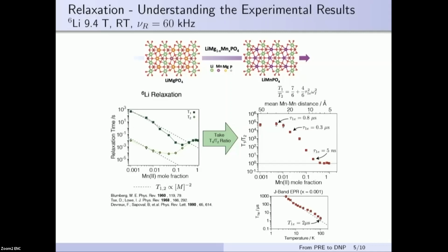So we wanted to know if these estimations are more or less correct. What we did is we were able to do some EPR relaxation measurements at high fields for the lowest concentrated sample for temperatures up to 100 Kelvin. At 100 Kelvin, we had a T1e of about 2 microseconds. If we extrapolate it to room temperature, which is where we did the NMR, we see that we are at least more or less in the right order of magnitude. And Ilya Kuprov told us this morning that in solid state, relaxation being in the right order of magnitude is the best we can get. So we're happy about this.